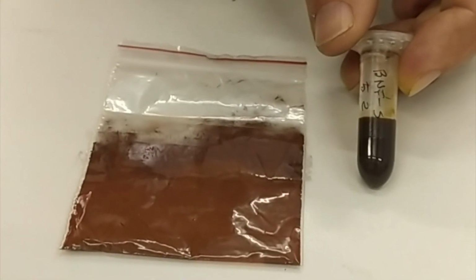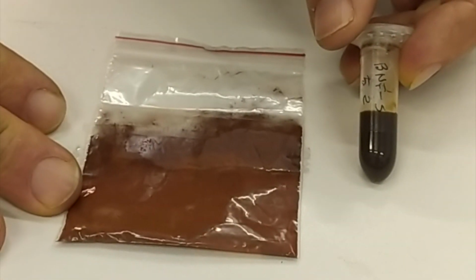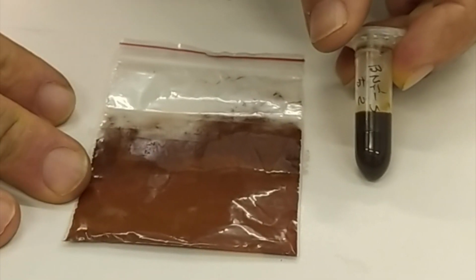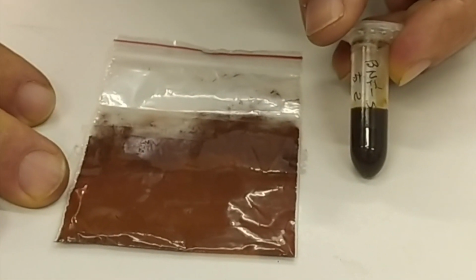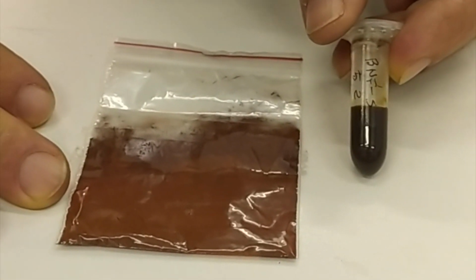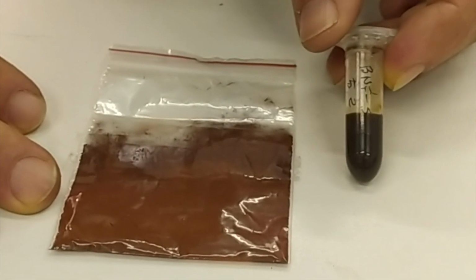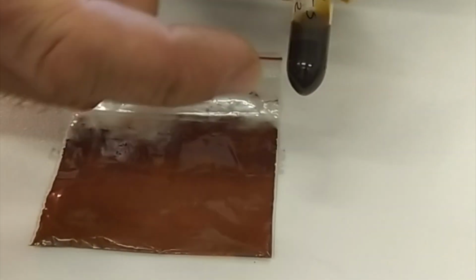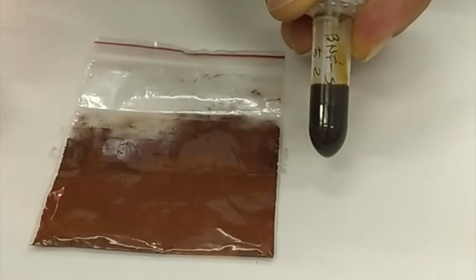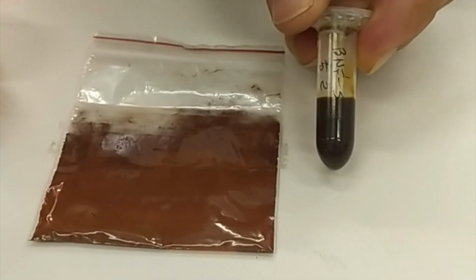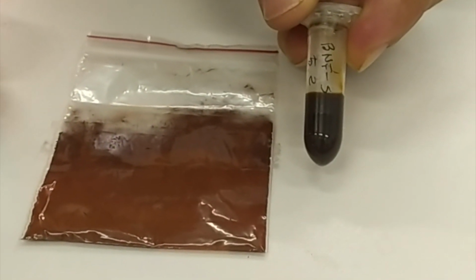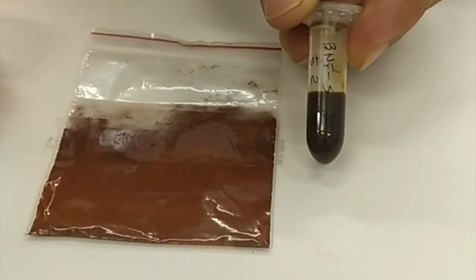In order to prepare the sample, you start with the dry nanoparticles. You take some of them, weigh them, and disperse them in a known amount of liquid. For example, 1 milliliter of water. This is an already prepared sample. The medium can be any liquid, in fact, but we chose water because its thermodynamic properties are well known.